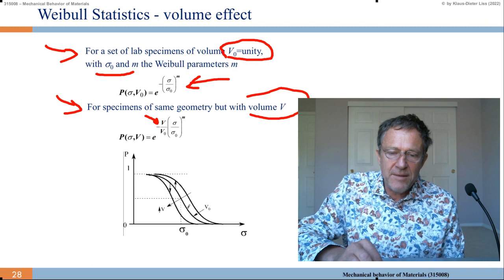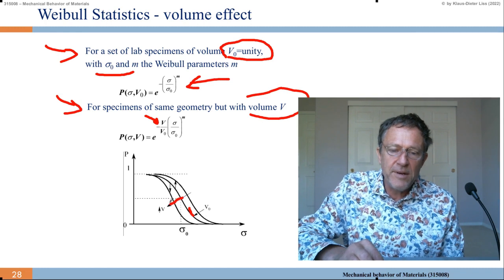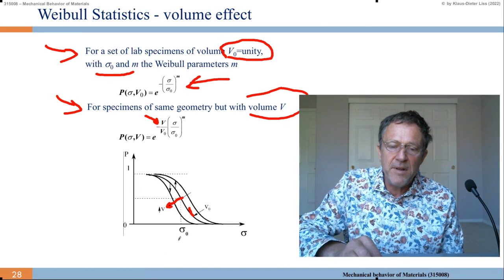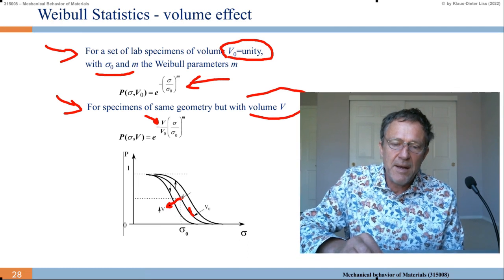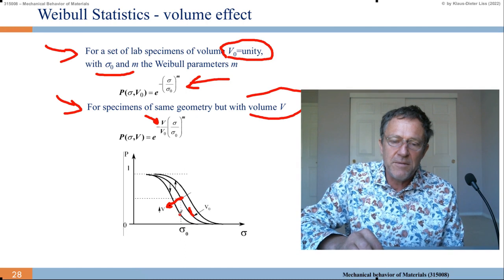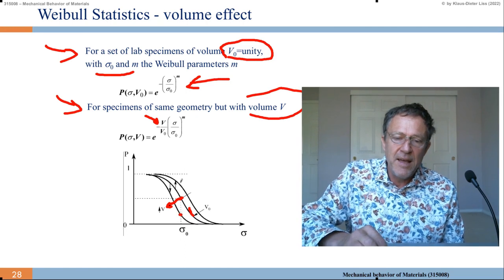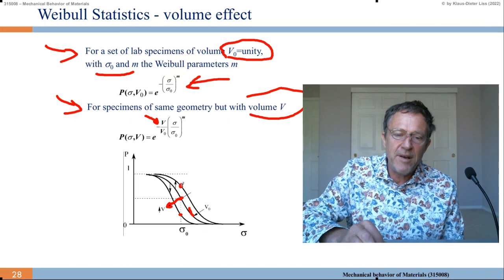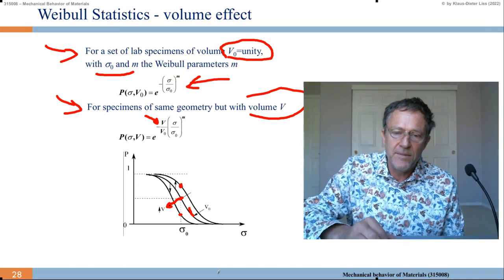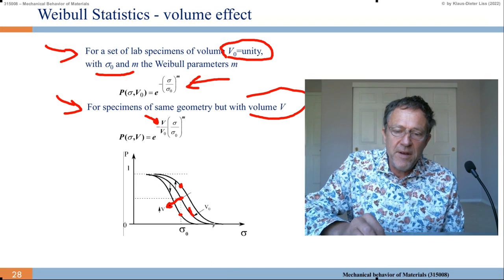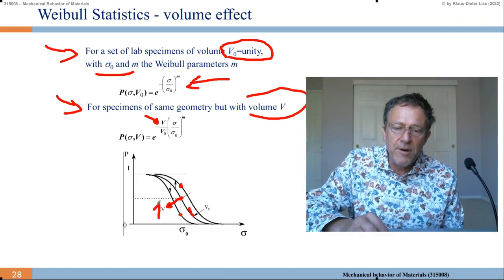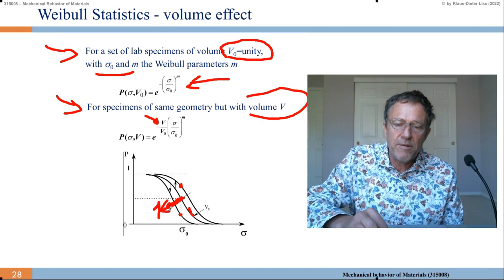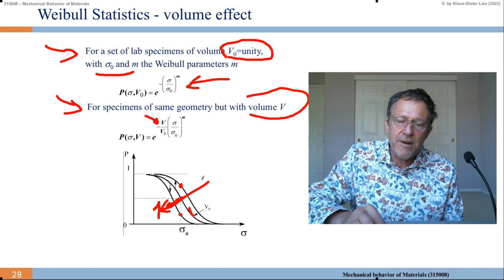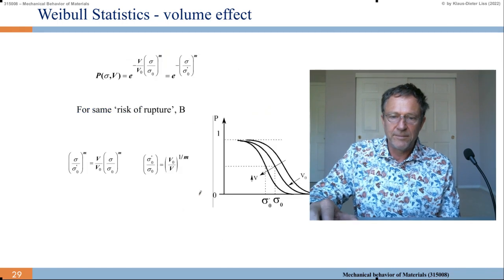So here the middle curve, the central curve, is for the volume V0. Now if I increase the volume, then I go down here with the probability. And that we know already, because if you have 50%, if you double the volume, then it goes down to 25%. We have said that already before. If I make the volume smaller, then I have a higher probability of survival. So evident. Just remember, if I have a V0, if I increase the volume, I go in this direction with my curve. And obviously, if I decrease the volume, I go in the other direction. This is nice to remember.